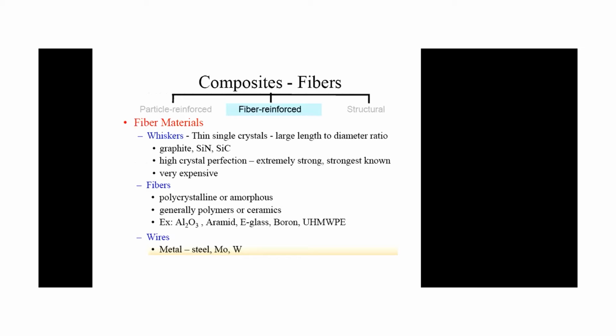So fibers can be alumina, aramid, e-glass. E-glass basically glass fiber, boron. So fiber polycrystalline. And as you know, any polycrystalline material has a certain defect at the grain boundary. Because of that, it has a lower property. But any material which is in a single crystal form, which are without any defect, that have a much higher property as compared to polycrystalline.